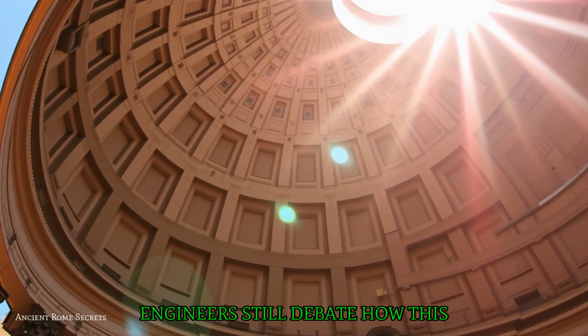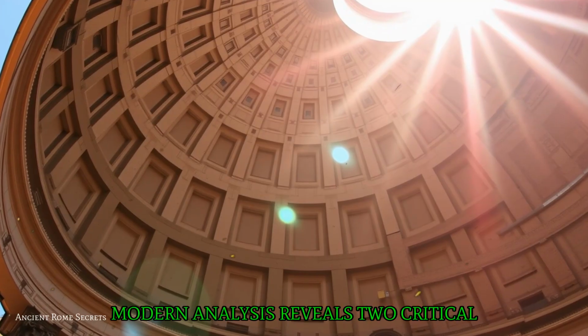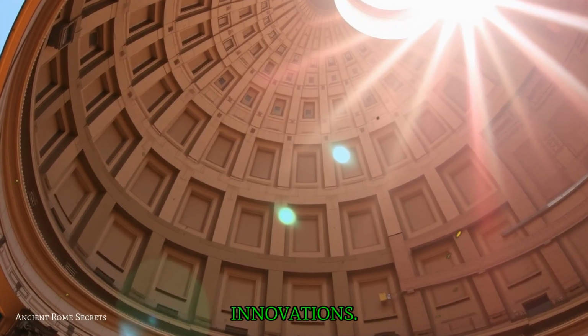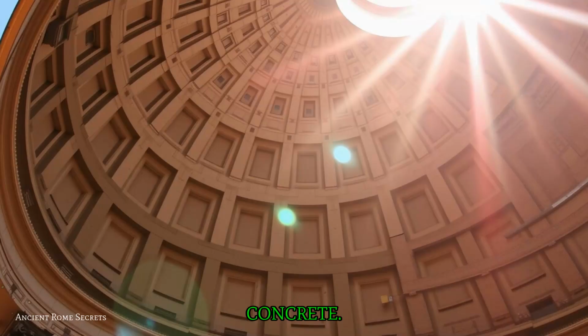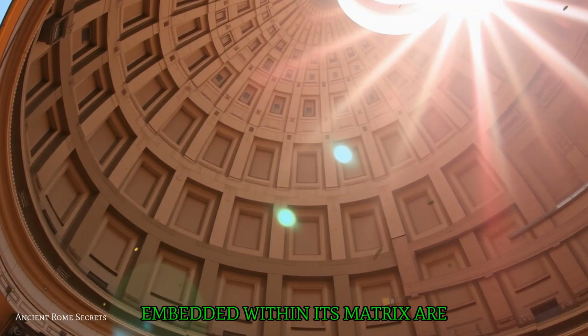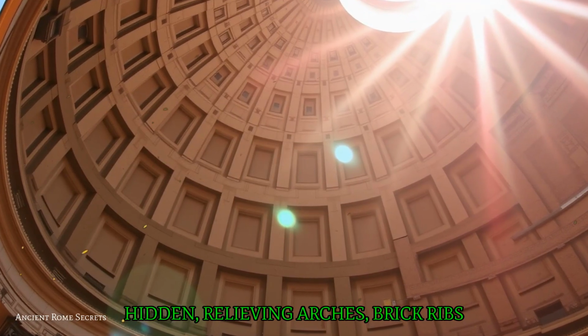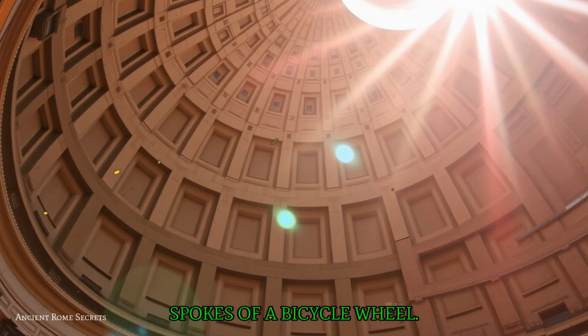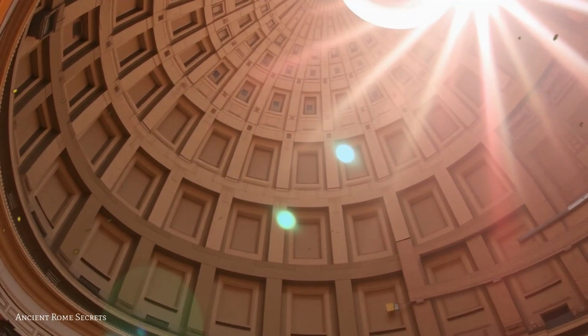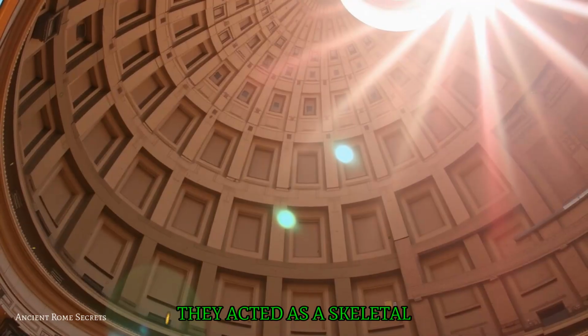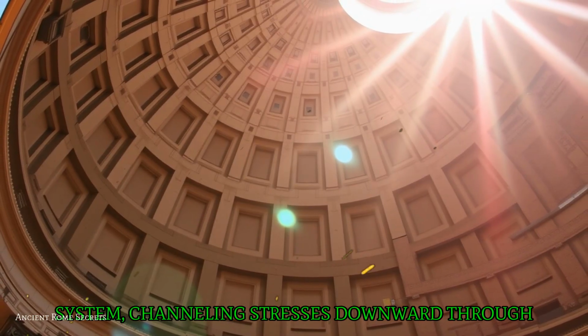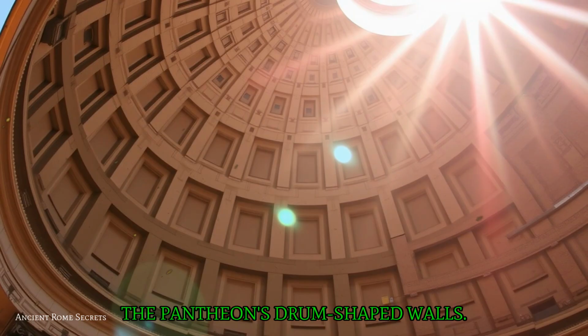Engineers still debate how this structure defied collapse. Modern analysis reveals two critical innovations. First, the dome isn't pure concrete. Embedded within its matrix are hidden, relieving arches, brick ribs that redistribute weight like the spokes of a bicycle wheel. These weren't decorative, they acted as a skeletal system, channeling stresses downward through the Pantheon's drum-shaped walls.